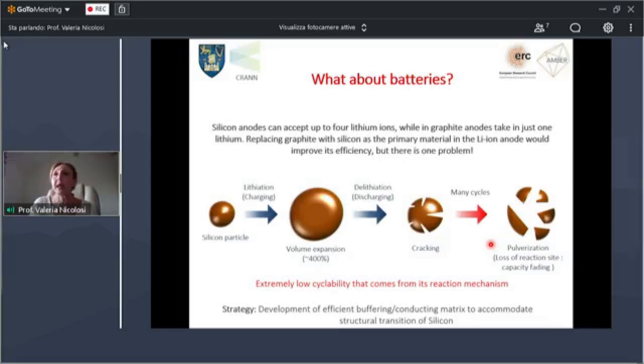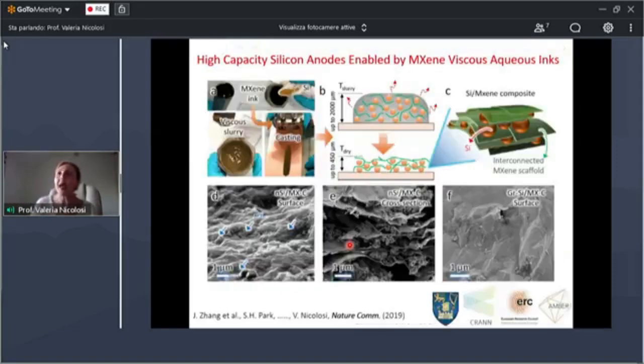Normally, what you would find in the solutions in the literature is that they add a polymeric binder to mitigate this volumetric expansion, and they also add carbon black as a conductive agent to maintain the performance of the electrode. Our solution instead was to replace both the carbon black, the conductive agent, and the polymeric binder with MXenes. We developed a methodology to mix silicon nanoparticles and MXene inks in water, make a slurry, and then cast this slurry exactly how the battery industry does.